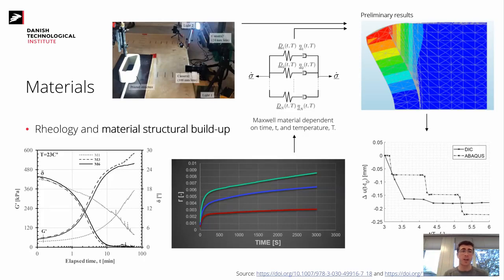When these two are combined, then we are in the sweet spot of 3D concrete printing. All of this work I'm showing here is still in progress here at DTI with a number of partners from Denmark. But the idea is that once these two models are combined, and I have a smooth transition between what's being described in the fluid domain to the elastic domain, or solid domain, of the material, then we can fully simulate a true printing process.